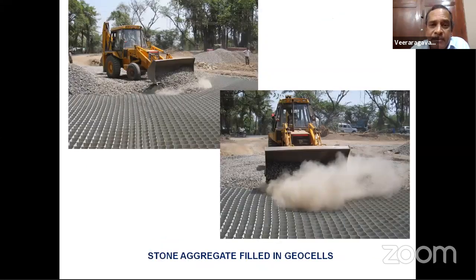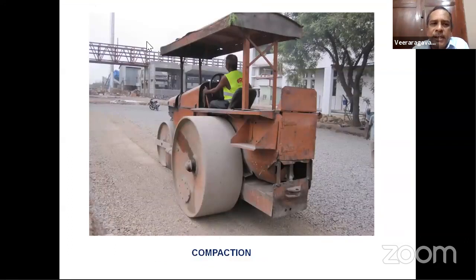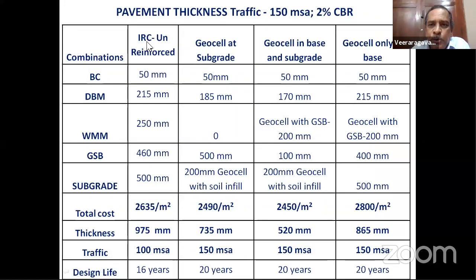What are the advantages here? If you look at the unreinforced section for a 2% CBR and about 150 MSA, I require nearly about 975 millimeter of pavement. On the other hand, if I use geocells in the subgrade, I can knock off the thickness, I can bring down 975 to 735. If I use geocells in the base and subgrade, I can bring down to 520. If I use geocells in the base, I can bring down to 865.